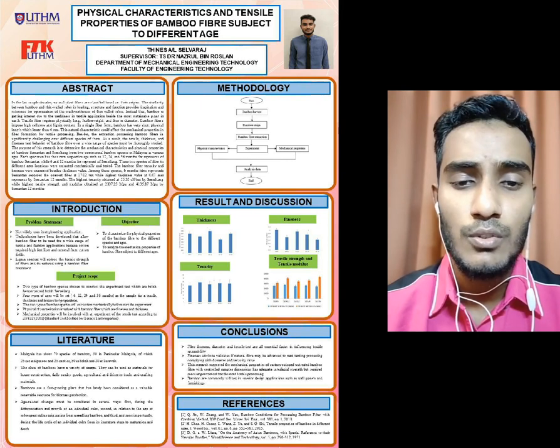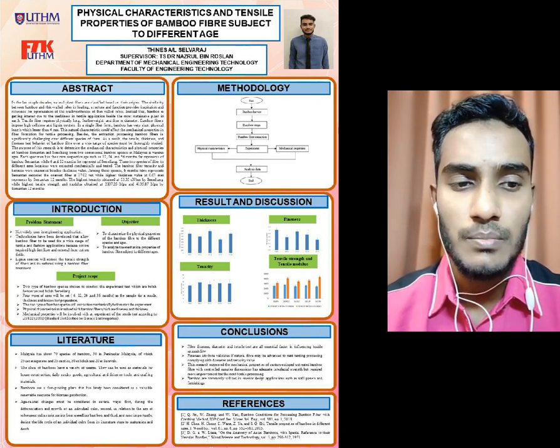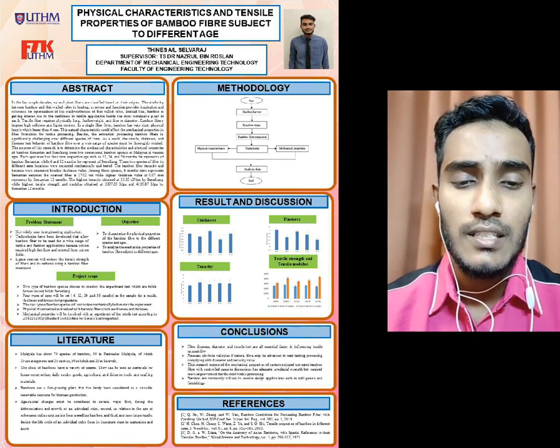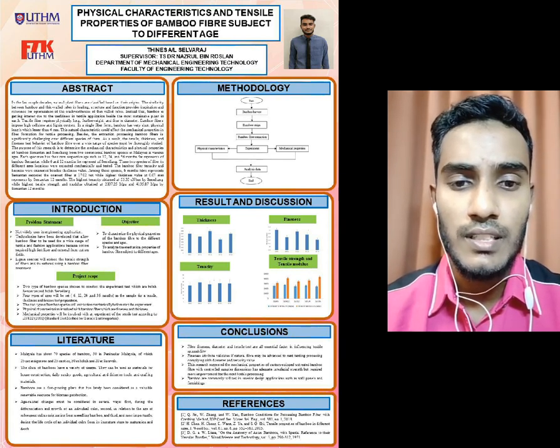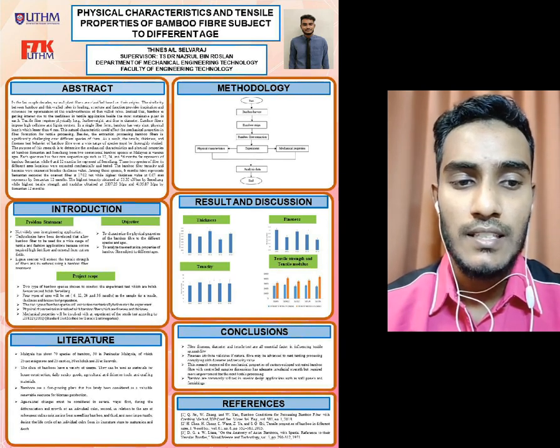Among those species, the 6 months fiber representing semantan recorded the coarsest fiber at 17.02 tex, while the highest thickness value of 0.07 represents semantan 12 months, and the highest tenacity was obtained by semeling 6 months at 55.33 cN per tex, and the highest tensile modulus obtained by semantan 12 months. Bamboo fiber has an advantage over other plant fibers owing to its fast growth rate and high strength, which has sparked academic interest in using bamboo fiber.